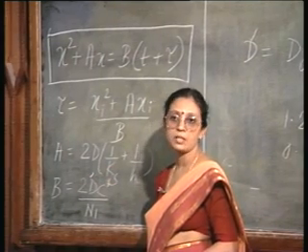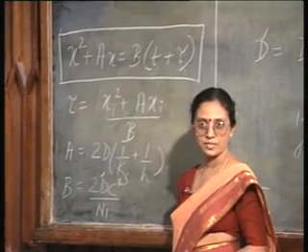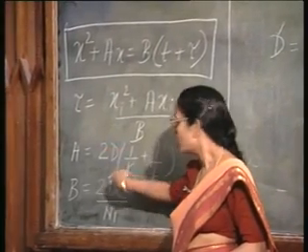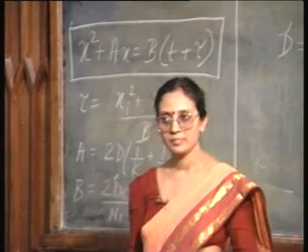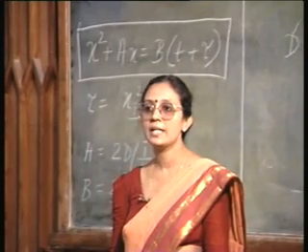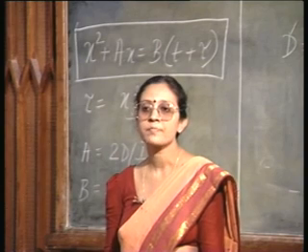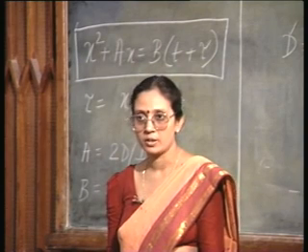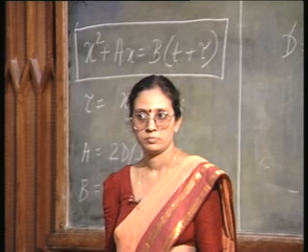Both of them are increasing with temperature. So, what actually happens to A depends on which one is dominating, D or Ks. That is why we find that A is actually decreasing with temperature, although both the linear and the parabolic rate constants increase with temperature. Okay.